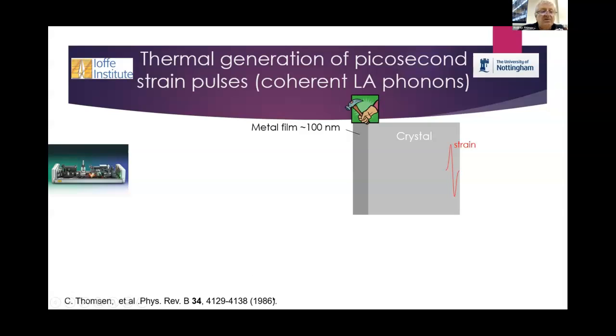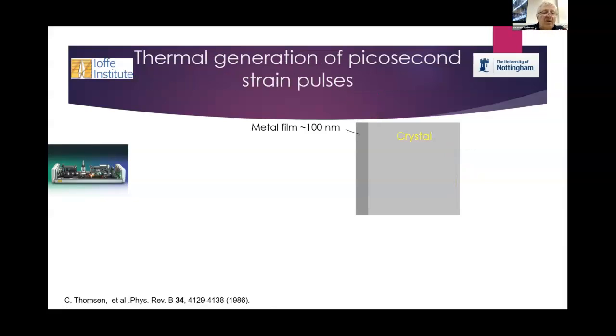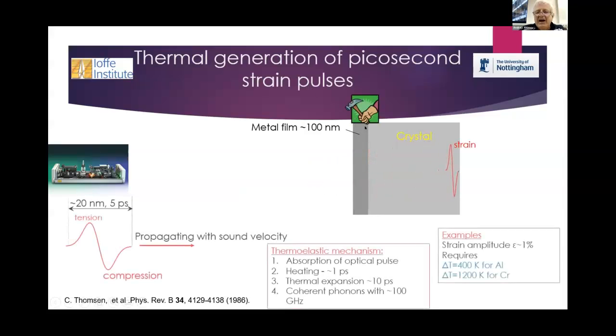In 1986 there was a famous work by Thomsen and Maris where they generated strain pulses in such a way. Let's look once more at how it works: the pulse hits the film like a kick of a hammer, and the strain pulse is injected. In the simplest way, this strain pulse is bipolar—first a compression part, then a tensile part—and it propagates with sound velocity, in most cases the longitudinal sound velocity, since it's only a compressed wave.